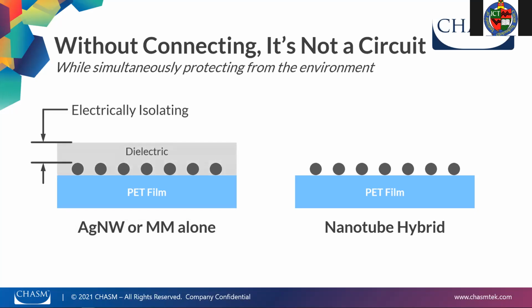So in order to provide environmental stability to these silver conductors that are typically used, some form of overcoat is required for the silver nanowire or metal mesh films alone. This does provide protection, but it also serves to electrically isolate precisely the conductive layer that you need in order to connect to create your circuit. So creating a good connection for your desired circuit, in this case, requires bridging the gap by etching, abrasion, or laser ablation, which in turn exposes a path for environmental degradation to the silver down below.